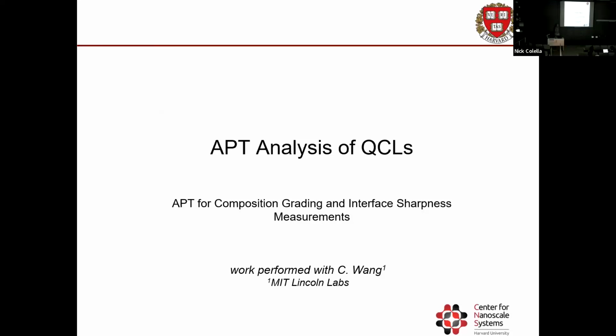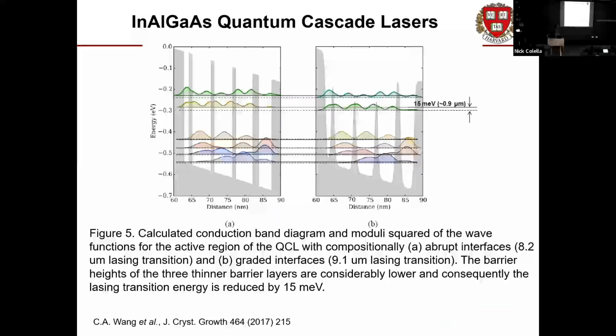How about interfaces? Everyone likes interfaces, right? Here's a different theoretical light emitting object called a quantum cascade laser. These get made at CNS, they get made other places, they're really neat. It's basically electrons in, laser light out on a chip, which is a pretty cool thing to be able to do. But to make it work, you have to build a structure which has very, very sharp changes in composition over very short distances, and everything has to be just the right thickness so that the energy landscape that the electrons you inject see oscillates in just the correct way, and it causes it to emit coherent light. Neat. And once again, we had the case where somebody made one of these and the light it emitted was the wrong color.